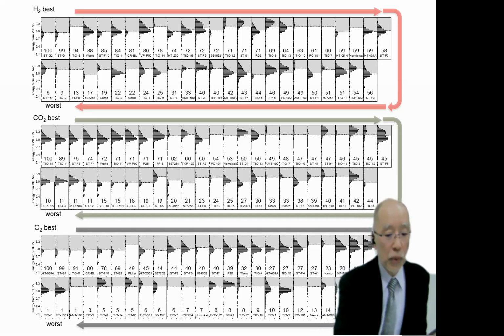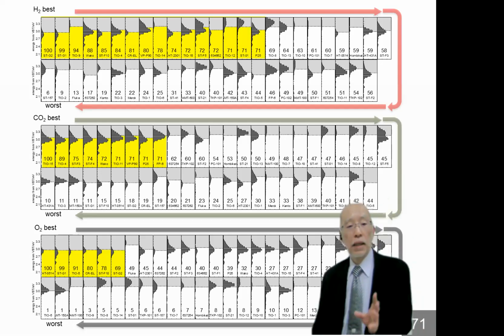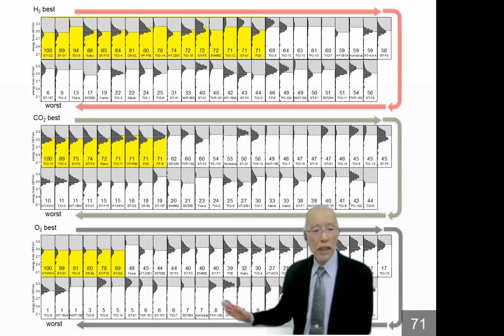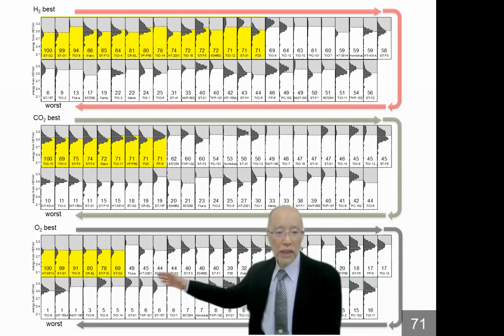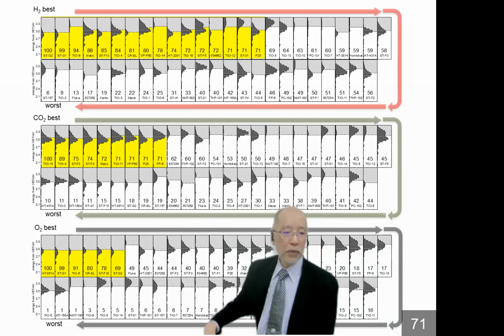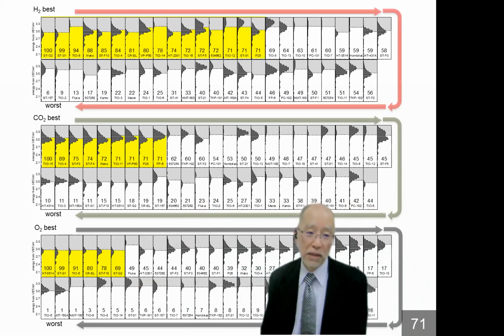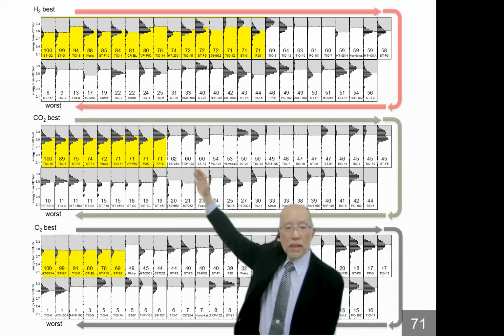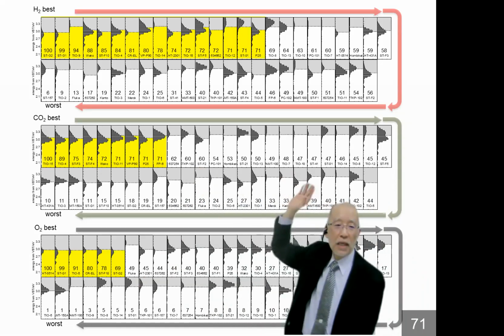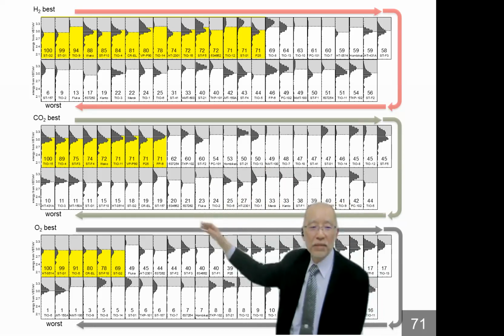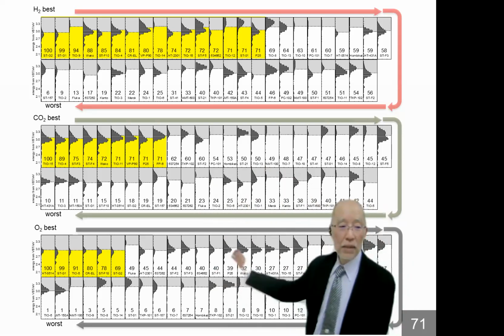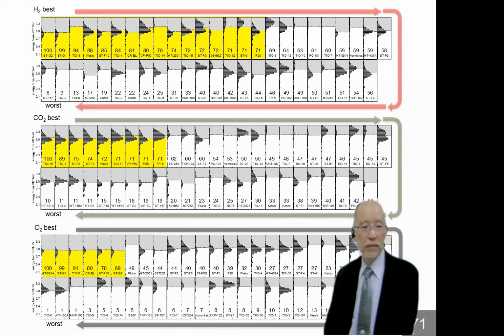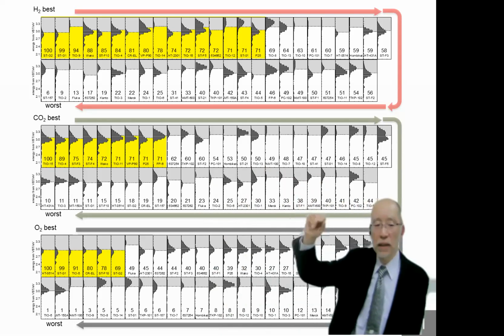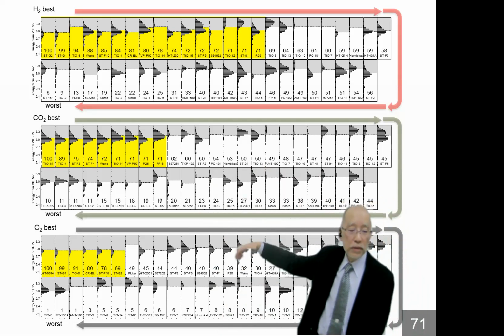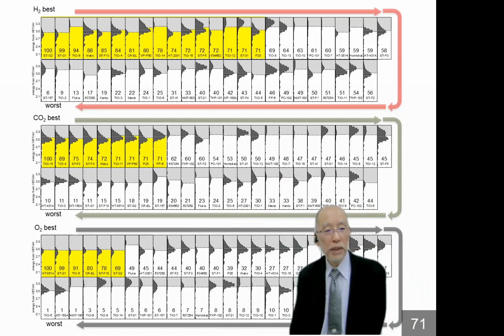But if you see the patterns of relative activity higher than about 70%, the yellow ones, for the carbon dioxide and oxygen evolution cases, they are similar, not so different. But below 70% relative activity, the neighboring patterns are not the same. Completely different patterns appear in middle or low activity samples. And for the hydrogen evolution case, no similarity can be obtained. For those two reactions, what does it mean?